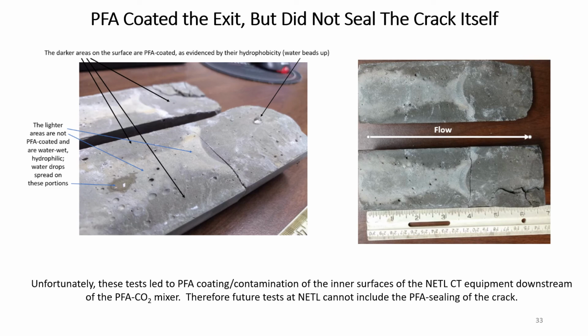Even still, we got some absorption of PFA onto the cement, as seen by the darker coloring of the cement in these pictures and its increased hydrophobicity. You can see by the fact that a water droplet on the darker part beaded up, while on the lighter part it spread out, giving us an indication that PFA was present on the darker surfaces.